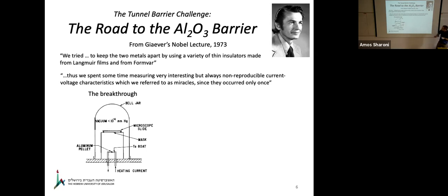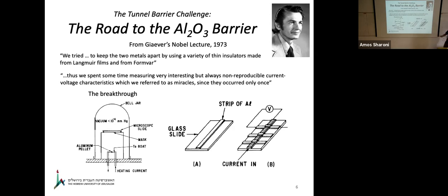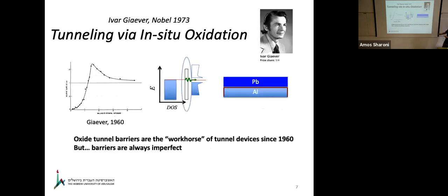What they did is the following thing. They used an evaporator, which is basically a vacuum chamber. They evaporated aluminum, and then if you evaporate an aluminum strip and very controllably introduce a small quantity of oxygen into your chamber, you have a thin layer of oxide. The special property of aluminum oxide is that it envelops the entire layer of aluminum, and it is a very clean, very homogeneous oxide layer. And eventually what he did was use some kind of a mask to create one layer, oxidize it, then create another layer. And then he has this tunnel junction which exists between these two layers.